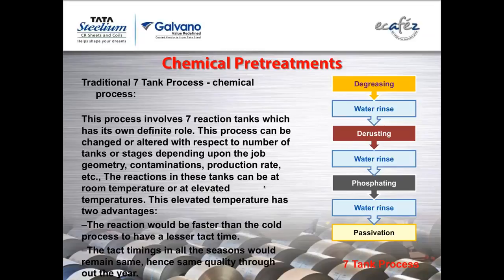But sometimes I've seen in most of the shops, one batch or one basket or two baskets will be there at the end of the shift, and the next day morning they process them. Not a very good idea. It can lead to certain problems. So basically, if possible, you can stagger the shift for the pre-treatment people and the shift for the coating people by say 15 minutes or half an hour depending on your productivities, and that could solve the problem, and your qualities will be under much more controlled, sustainable control.